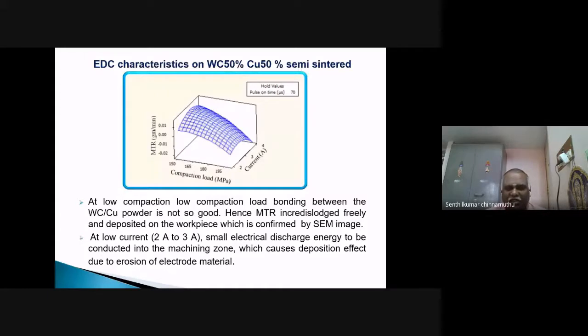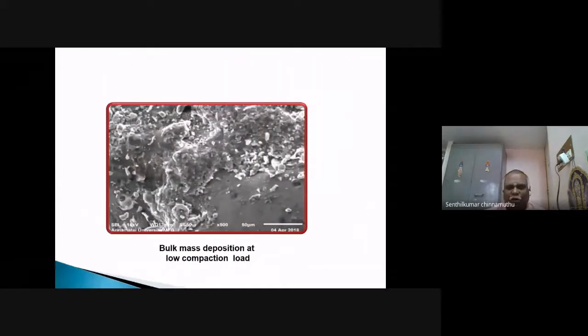See the surface morphology at this low compaction load. The bulk mass deposition takes place. Bulk mass means at low compaction load, the compaction is very less, that is 150 megapascal. The particles are loosely bonded and easily disintegrated from the tool material, and it is deposited non-uniformly. It is deposited as bulky.